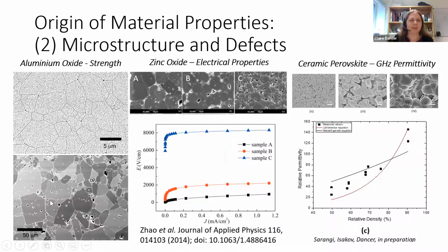And these are both the same material. They look quite radically different when we look at their microstructure. So this is what we can see under the microscope. You can see here that we have a much more pure, much fewer defects piece of aluminium oxide here, and the grain structure is much finer. This is a 5 micron bar, this is a 50 micron bar.